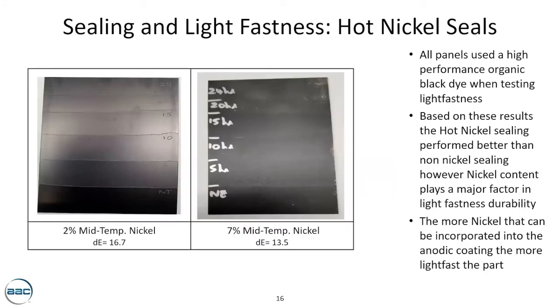Next one is hot nickel seals. In this particular test, we used our mid-temperature seal with 2 different concentrations of nickel. Even in this test, the panels used were made with high performance organic black dye. Based on these pictures, you can see that hot nickel sealing performed way better than non-nickel sealing. However, the concentration of nickel in the seal plays a really important role in light fastness durability. So by looking at this, we can say that the more nickel we can incorporate in the coating, the more light fastness a part will have.